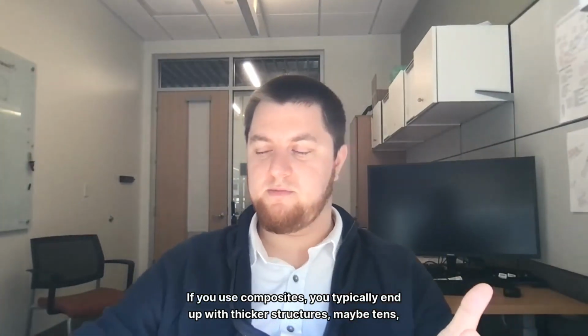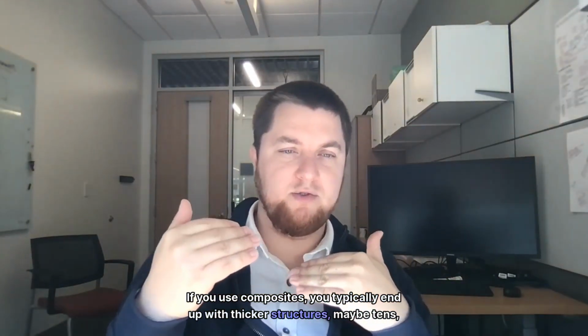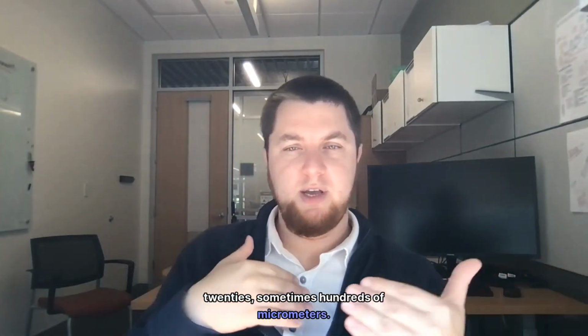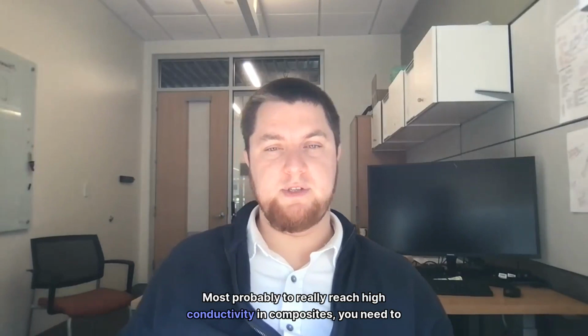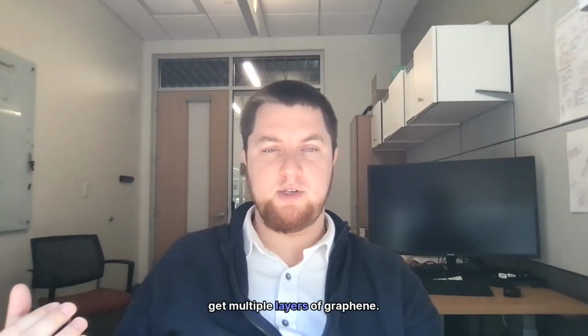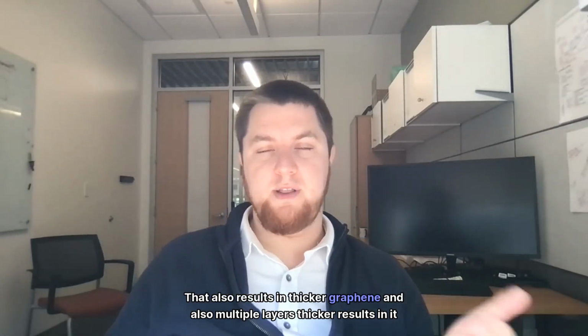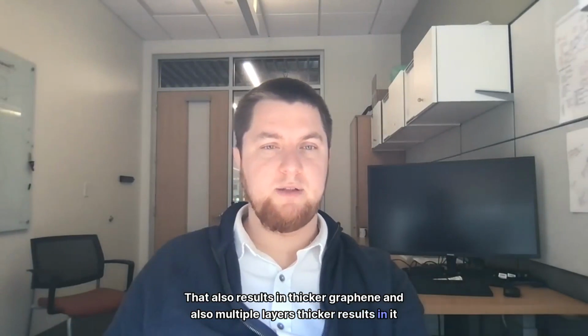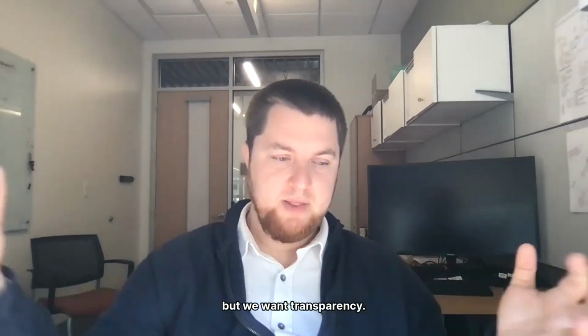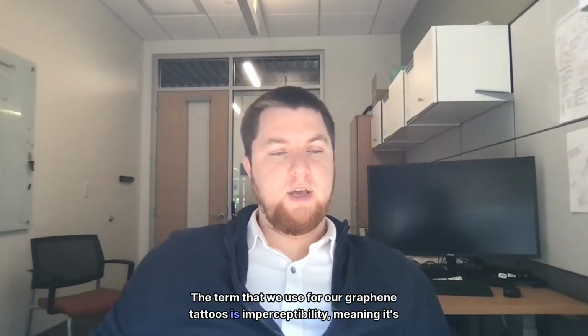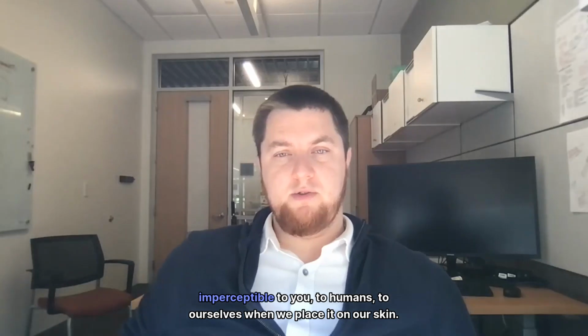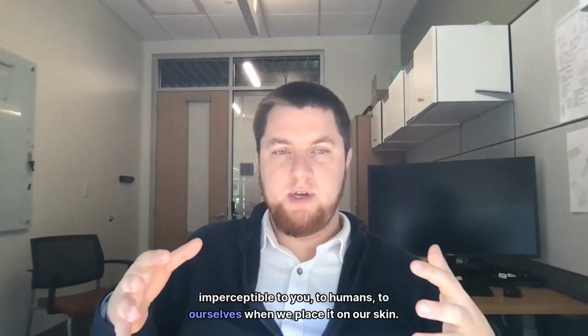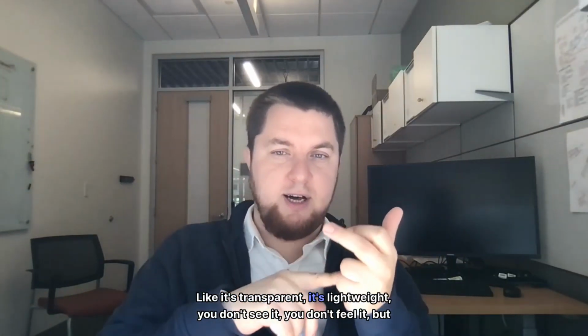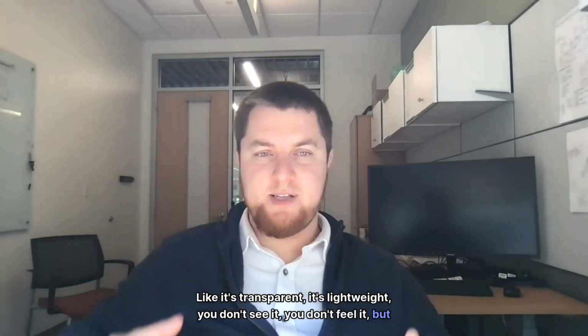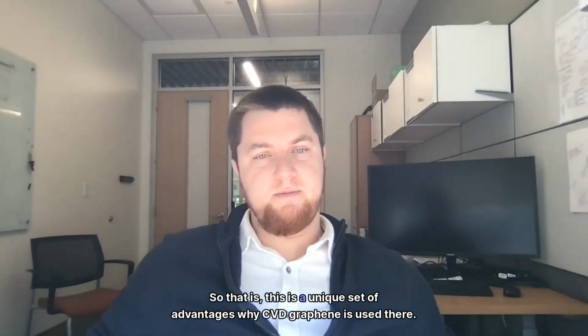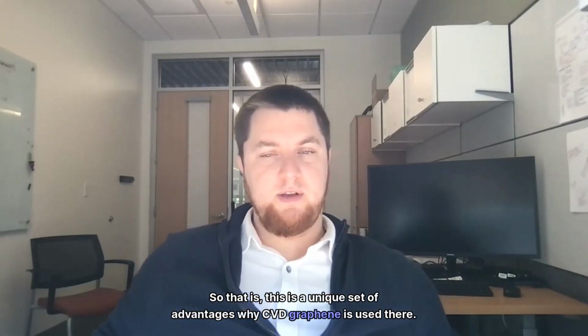If you use composites, you typically end up with thicker structures, maybe tens, 20s, sometimes hundreds of micrometers. Most probably, to really reach high conductivity in composites, you need multiple layers of graphene. That also results in thicker graphene, and multiple layers make it non-transparent. But we want transparency. The term that we use for our graphene tattoos is imperceptibility, meaning it's imperceptible to humans, to ourselves, when we place it on our skin. It's transparent, it's lightweight, you don't see it, you don't feel it, but it's there. So this is a unique set of advantages for why CVD graphene is used there.